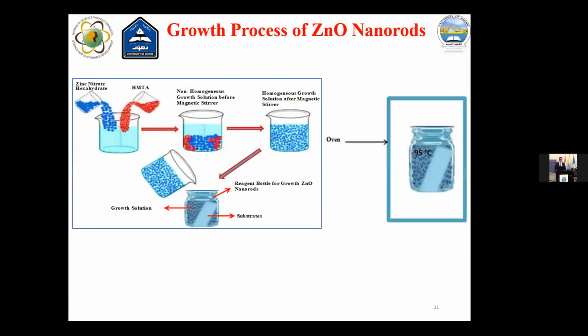The growth process of the zinc oxide nanorods: first, zinc nitrate hexahydrate is dissolved in deionized water under a magnetic stirrer to get a homogeneous solution, and separately hexamethylenetetramine is dissolved under the magnetic stirrer to get a homogeneous solution. After that, the two solutions are mixed together under the magnetic stirrer to get the homogeneous growth solution. After that, we